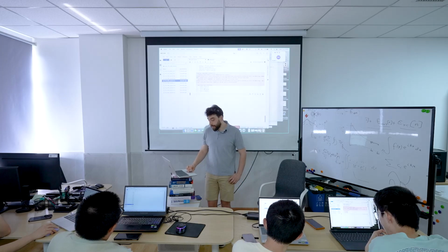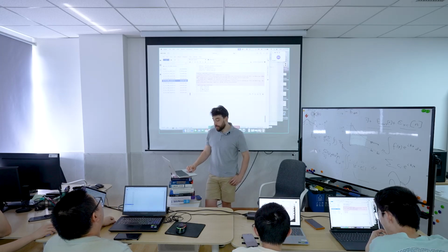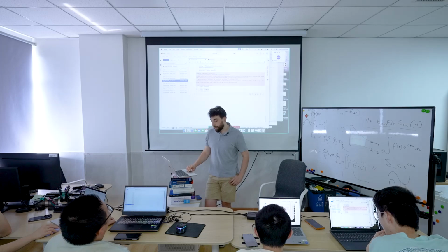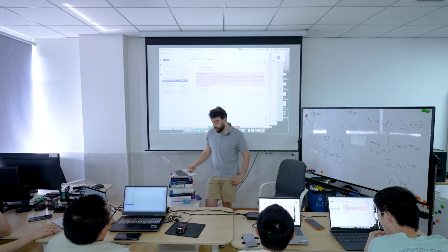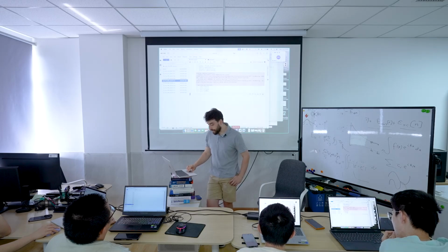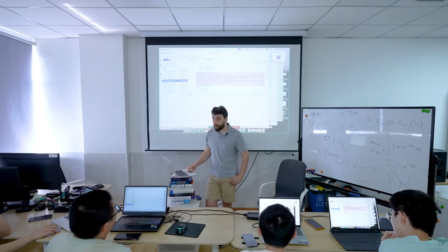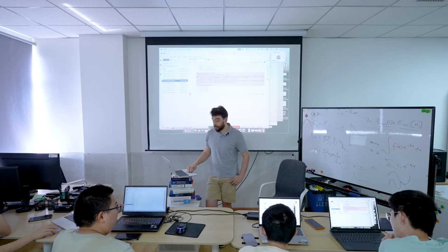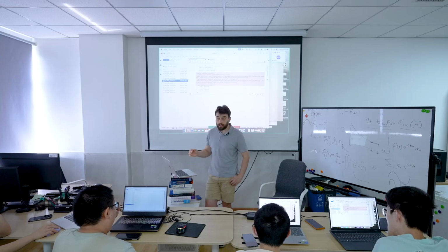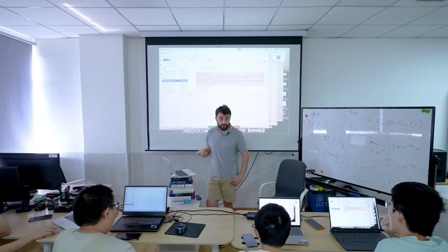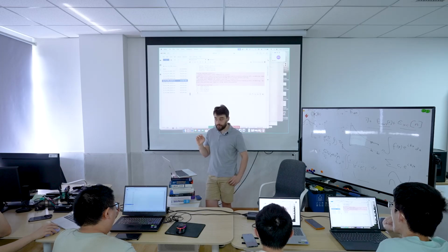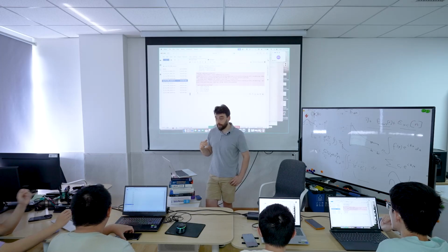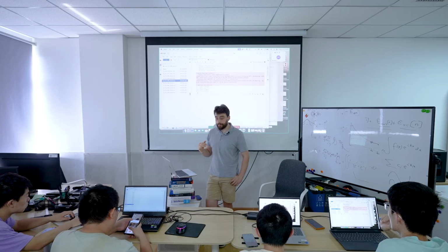Right. So by the time we get to 333, the difference between 222 and 333 is about 1. And then by the time we get to 444, the difference between 333 and 444 is about, well, 3 times 10 to the minus 1. Okay? 0.3. So what I expect now is probably 555 or 666 will have good convergence. The difference between them will be less than 10 to the minus 2. Okay.